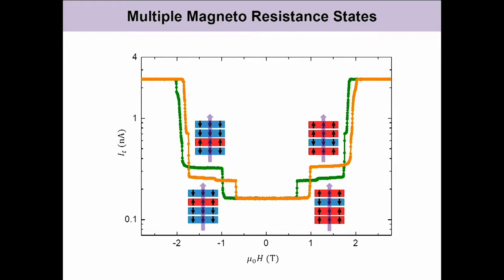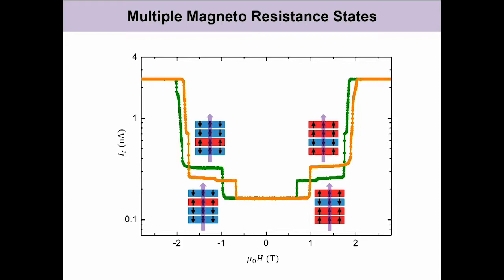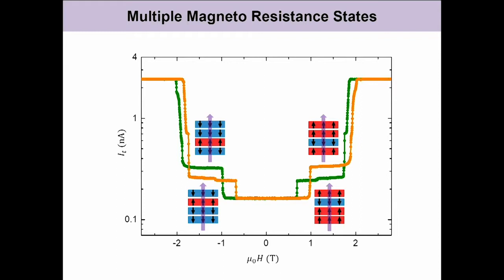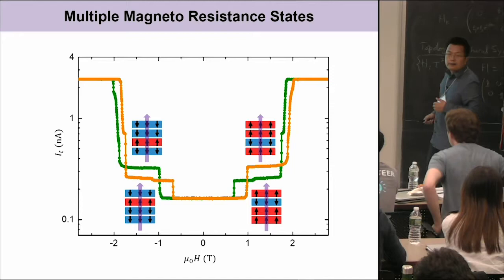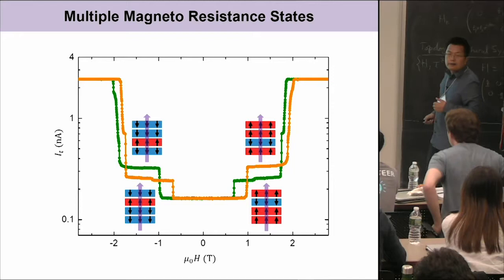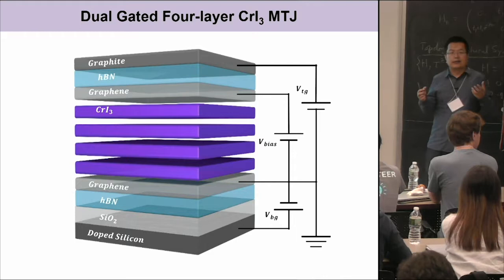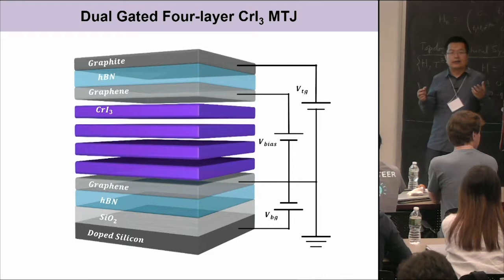You can see initially there's a plateau corresponding to one state, but for certain devices I can have a plateau with two different levels in the intermediate states. These two different levels correspond to the two different bistable states. This is a hint that we do have these two different bistable states, and there's a chance we can have both of them accessible by measurements.